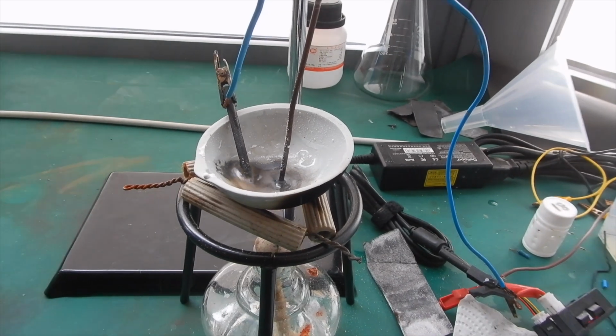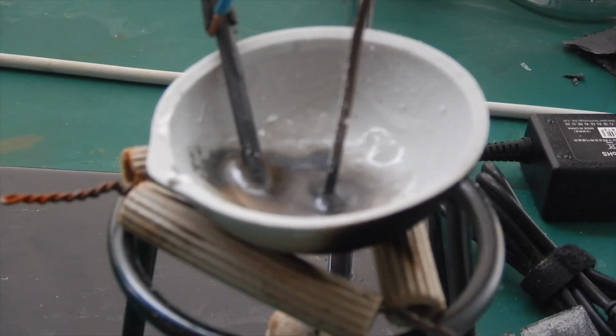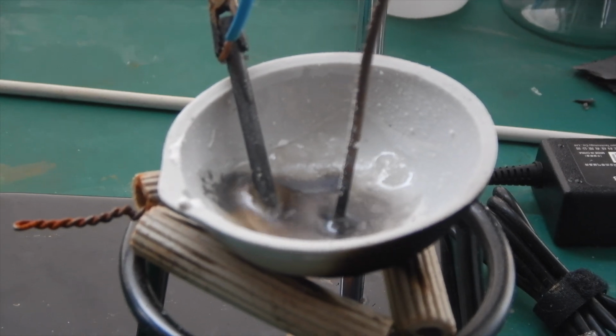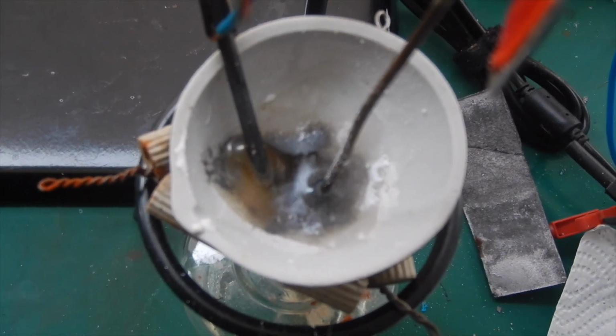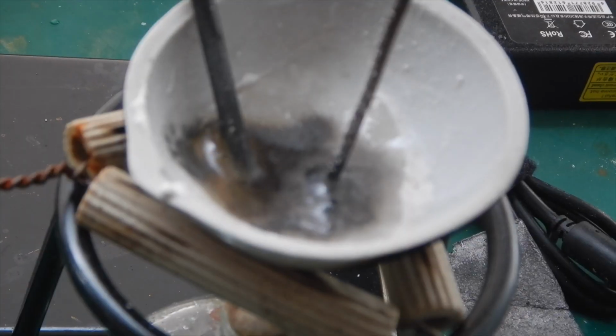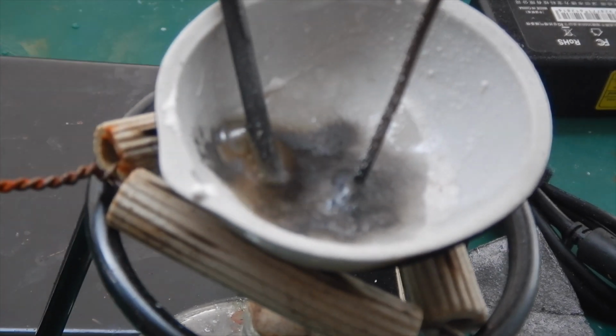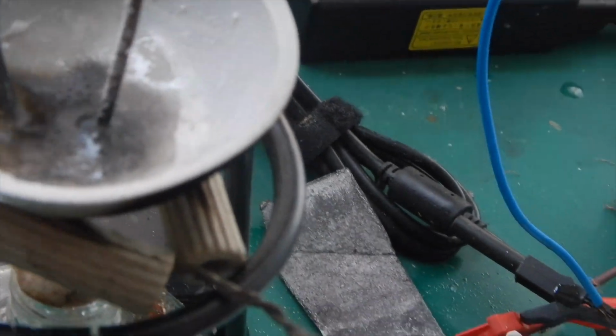The electrolysis had proceeded for a few minutes, and now the mixture is completely melted. A lot of bubbles are given off at the anode, and a shiny material can be seen around the cathode. This is our bead of molten lithium metal. I checked the meter, and the current was about 1.4 amps, which appears to provide enough heat to keep the mixture molten and not solidifying.